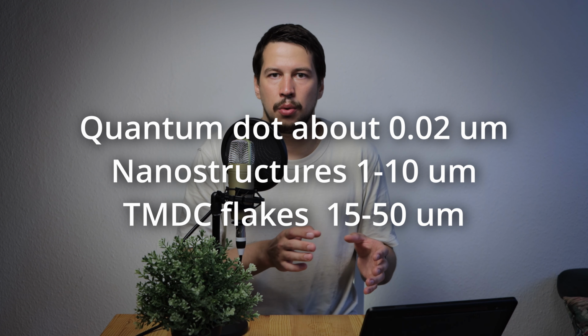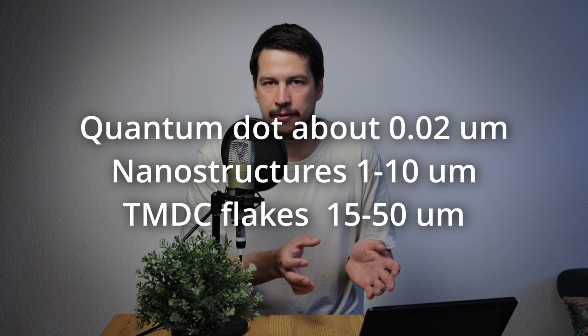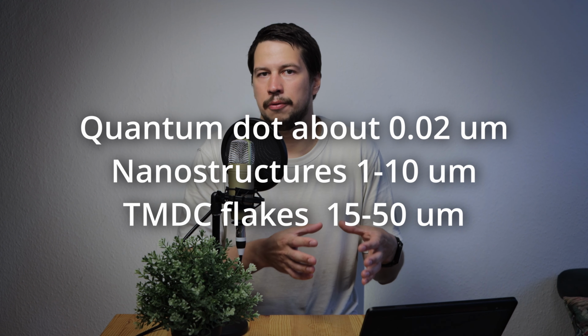The flake usually has size of 10, 20, 30, 50 microns. Some people can achieve even bigger size of flake, but it's already challenging. But basically, for nanotechnology, if you have some structure of size, let's say, tens of microns, it's already quite huge. For example, the quantum dots I'm working with have size of, let's say, way sub-micron, and even the nanostructures which we construct around them have size of, let's say, 3-5 microns, and here a flake of size 20 or 50 microns is already quite huge. So in the lab we study flakes, but I believe if the market is really interested in production of such material, it's possible to grow using epitaxy or something similar, as it was for graphene.